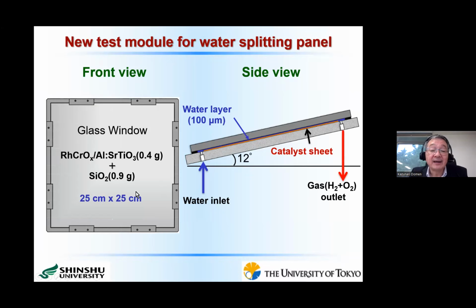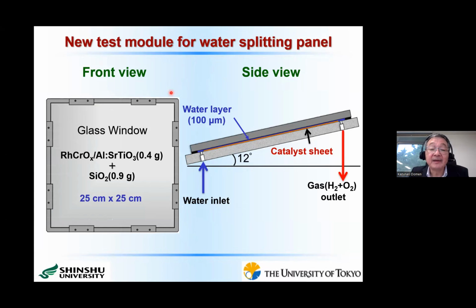Then we constructed a larger water splitting panel. In this case, we constructed 25 centimeters times 25 centimeters. The loaded photocatalyst is 0.4 gram, and silica nanoparticle is 0.9 gram. This is a side view of the water splitting panel. Here we have a photocatalyst layer, and this is a gas outlet. And here we have a water inlet. Water is very slowly introduced into this reactor, and the thickness of the water layer in this case is only 100 micrometers, 0.1 millimeter.